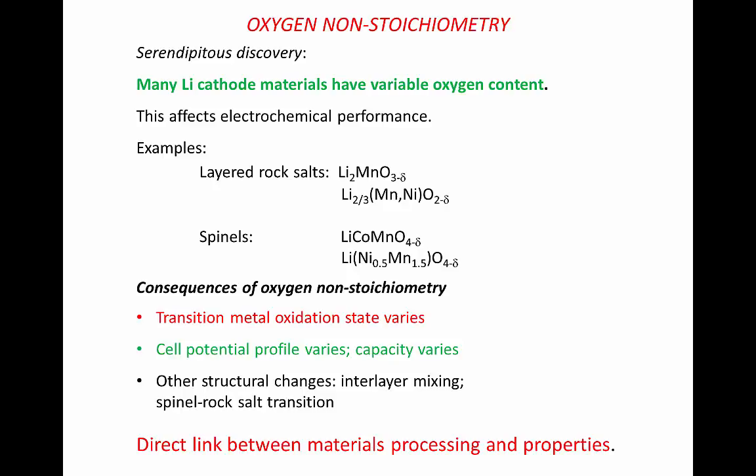So consequences of oxygen non-stoichiometry are that the transition metal oxidation state depends very much on the processing conditions, and in particular on the final cooling rate after synthesis.